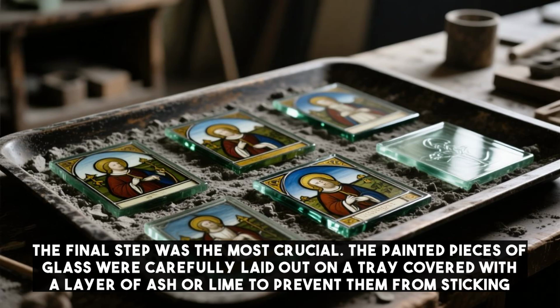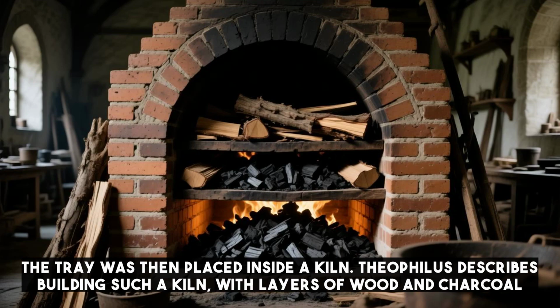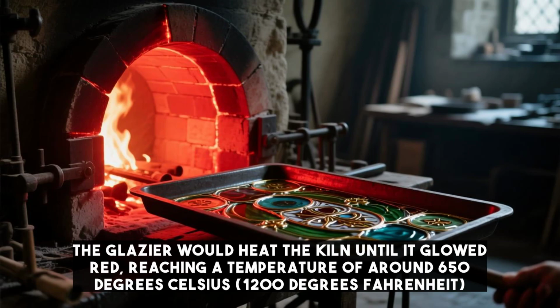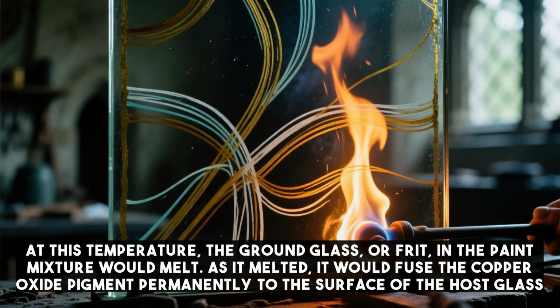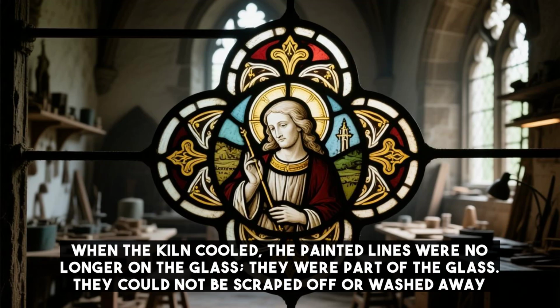The painted pieces of glass were carefully laid out on a tray covered with a layer of ash or lime to prevent them from sticking. The tray was then placed inside a kiln. Theophilus describes building such a kiln with layers of wood and charcoal. The glazier would heat the kiln until it glowed red, reaching a temperature of around 650 degrees Celsius, 1200 degrees Fahrenheit. At this temperature, the ground glass or frit in the paint mixture would melt. As it melted, it would fuse the copper oxide pigment permanently to the surface of the host glass. When the kiln cooled, the painted lines were no longer on the glass, they were part of the glass. They could not be scraped off or washed away.